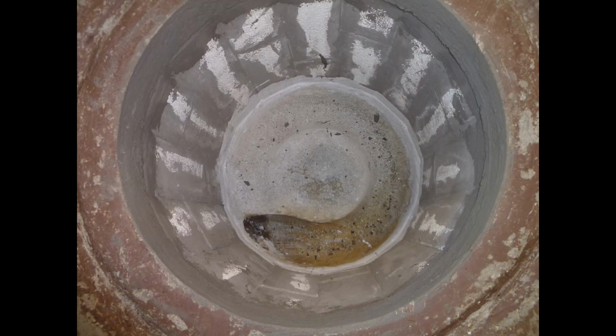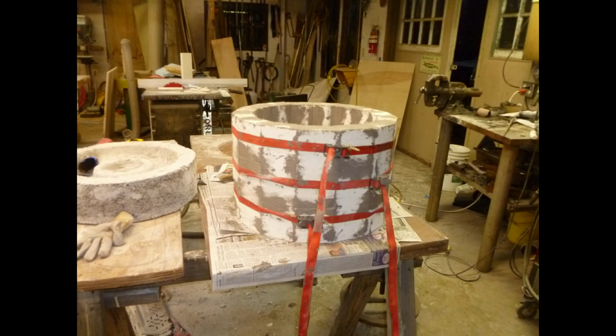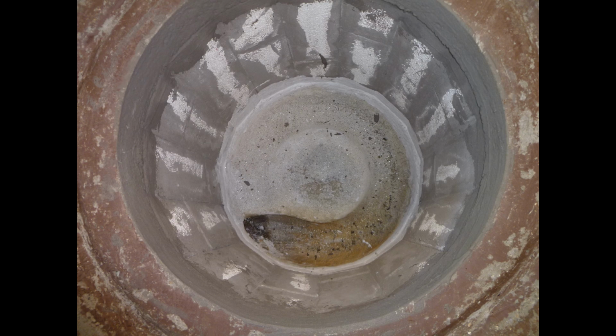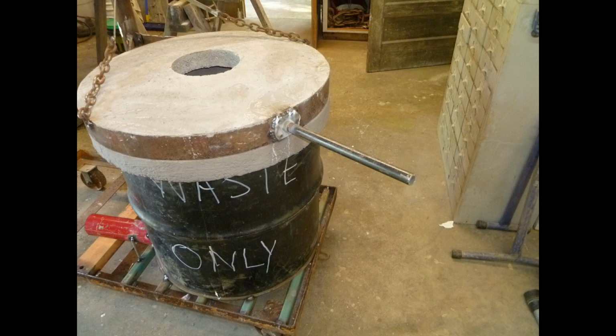This is looking down from the top before it's ever fired. You can see the cast refractory at the bottom, and then there's a row of insulating bricks that are soft, kind of chalky. You can cut them on a table saw. Behind the insulated bricks is a 1-inch layer of ceramic fiber insulation, and on the top is a refractory cap to hold it all together. In the beginning, there was a groove that linked the cap and the top so they fit without losing a lot of flame. That's kind of gone away now. It's crumbled. And the black paint, which came originally on the drum, is still mostly there, which is a testament to the insulation ability of the ceramic fiber insulation.